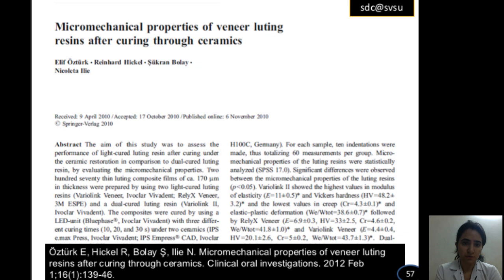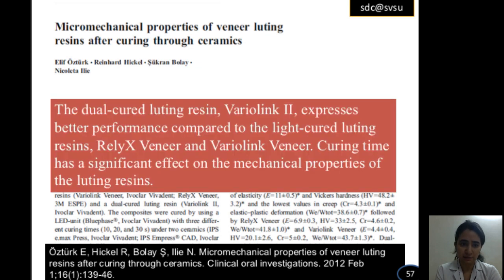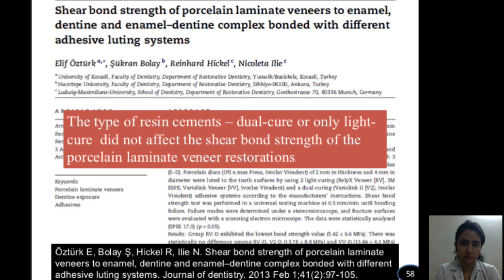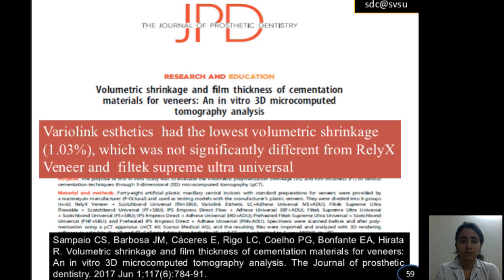On the micromechanical properties of veneer luting resins after curing through ceramics, they concluded that the dual cure resin cement expresses better performance than the light cure cements. The shear bond strength of porcelain laminate veneers to enamel, dentine, and enamel dentine complex bonded with different adhesive luting cements concluded that the type of resin cement, that is dual cure or only light cure, did not affect the shear bond strength of the porcelain laminate veneer restorations. A study on the volumetric shrinkage and film thickness of cementation material for veneers concluded that Variolink Esthetics had the lowest volumetric shrinkage of about 1.03%.